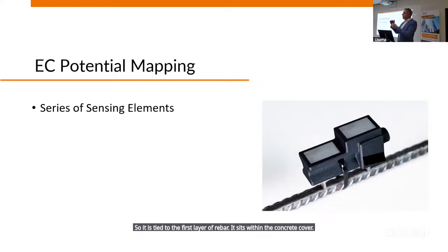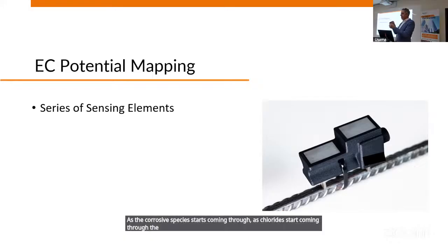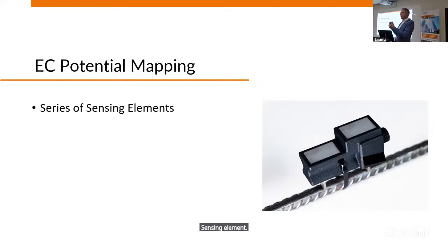As the corrosive species starts coming through, as chlorides start coming through the concrete surface and reach the top sensing element, its potential shifts. This corrodes. It becomes anodic to the rebar. And we monitor that shift in potential. And that informs us that we're getting activity at a certain level in a certain location. We have a second step to also validate that data and validate the insight. So over time, we would expect it to activate, and ultimately the rebar will activate.